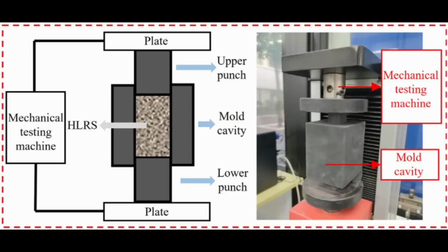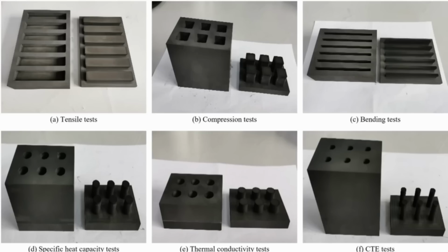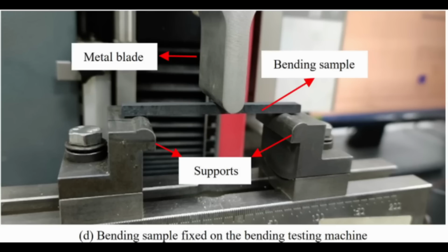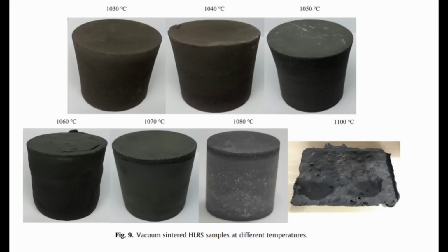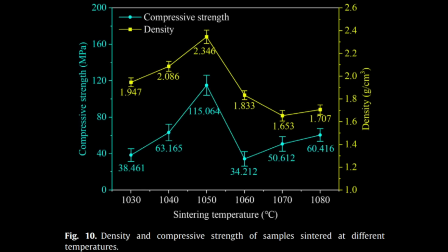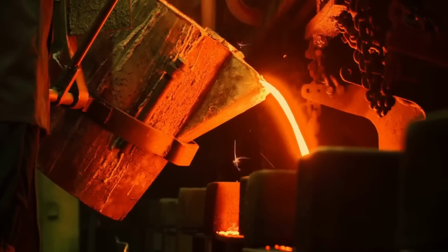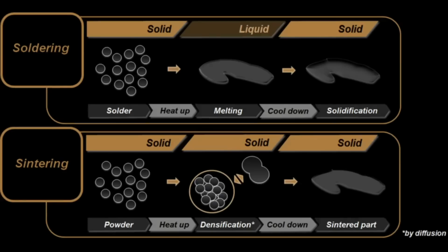This study measured the physical, mechanical, and thermal properties of vacuum-sintered lunar regolith simulant at different lower-end sintering temperature ranges. That part's important. And found that regolith sintered at precisely 1050 degrees Celsius has the best properties. Sintering is not melting, but it's close. When we melt something, all the individual particles turn into liquid and get mixed together, and when it cools, they reform as one solid mass.